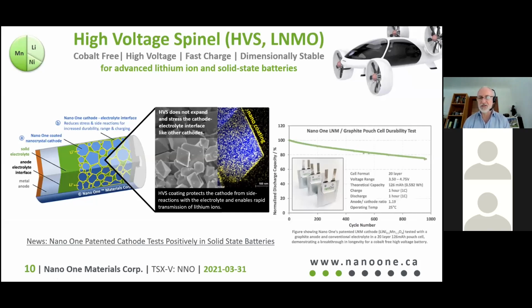We've been able to demonstrate that by using this, you can make a full cell graphite pouch cell with LNMO that eliminates gassing failure and eliminates contamination of the graphite. And we've run this for nearly 1,000 cycles. They said this couldn't be done. A lot of our partners said, it gasses like crazy, you can't do it. Well, we found that by taking our Nano One coated material and matching it with a commercially available electrolyte, we don't do electrolyte development, so it's just a commercially available electrolyte, if you get the right one, it'll last a long time. It's quite stable. We patented this process, and we're scaling it up with our cathode material partners.